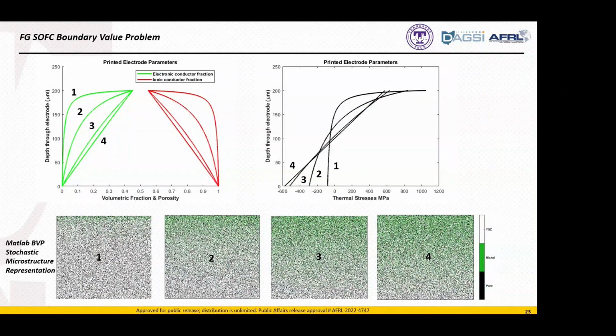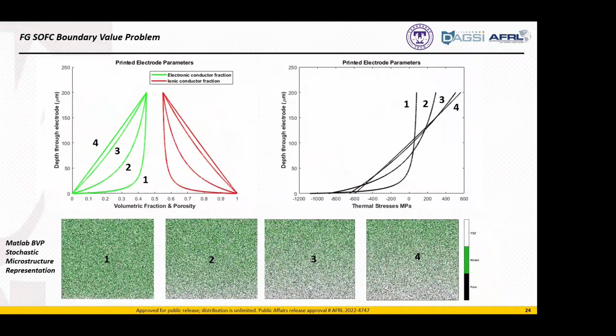Another thing that we had done is added a thermal stress model to the electrode so that we can track the thermal stresses, the tensile and the compressive thermal stresses that are present in the cell, just as a result of the thermal expansion coefficient mismatch between, say, a nickel and a YSZ in an electrode. And here you see the various grading profiles, and then on the bottom, a representation of what the MATLAB program is actually computing on. And then here's the profiles flipped.